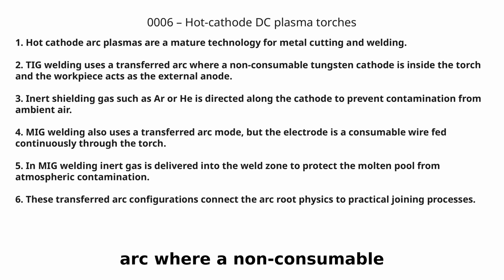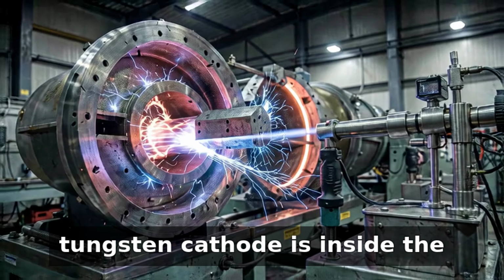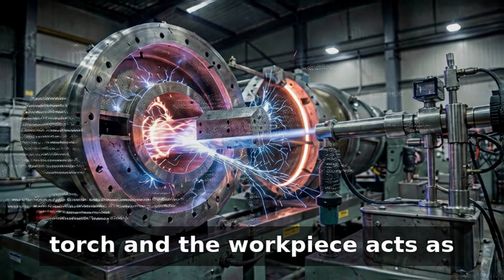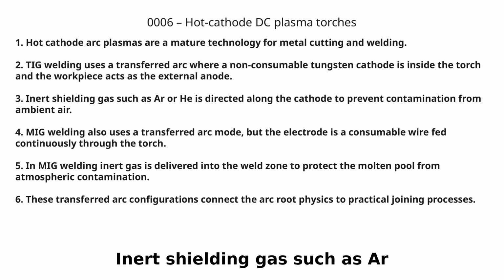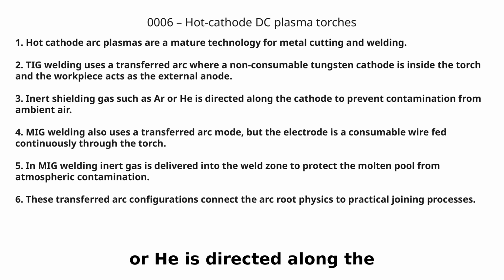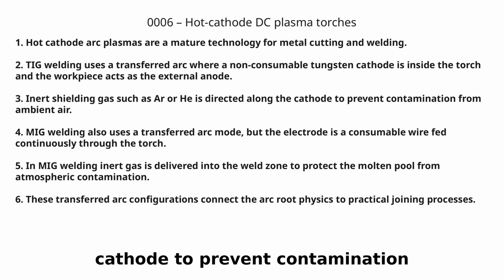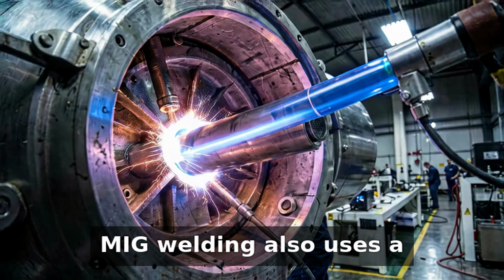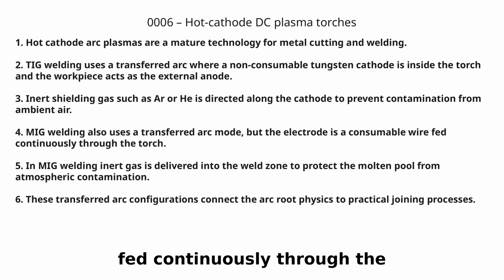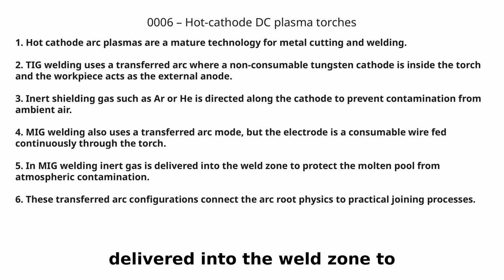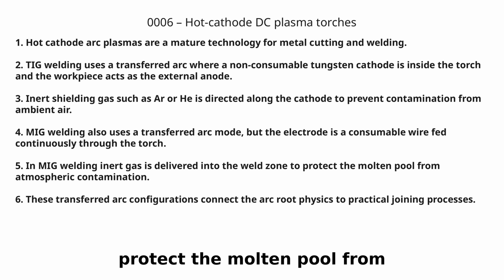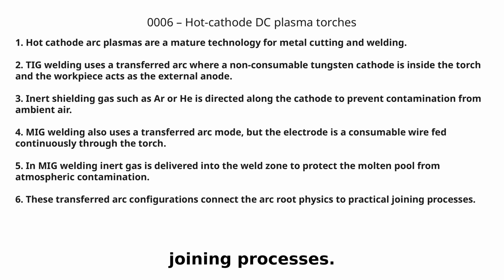TIG welding uses a transferred arc where a non-consumable tungsten cathode is inside the torch and the workpiece acts as the external anode. Inert shielding gas such as argon or helium is directed along the cathode to prevent contamination from ambient air. MIG welding also uses a transferred arc mode, but the electrode is a consumable wire fed continuously through the torch. In MIG welding, inert gas is delivered into the weld zone to protect the molten pool from atmospheric contamination. These transferred arc configurations connect the arc root physics to practical joining processes.